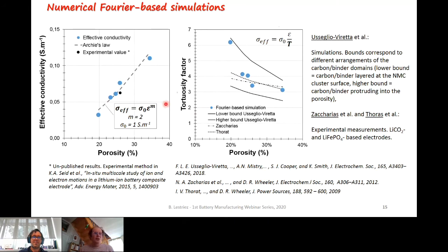On the left, you have plotted the effective conductivity as a function of the porosity. For the FIB-SEM volumes, the results are the blue dots. They are well fitted by an Archie's law with an exponent equal to 2, which is an acceptable, expected exponent for such a porous composite medium. And we have a good agreement with the only experimental value we have at the moment.